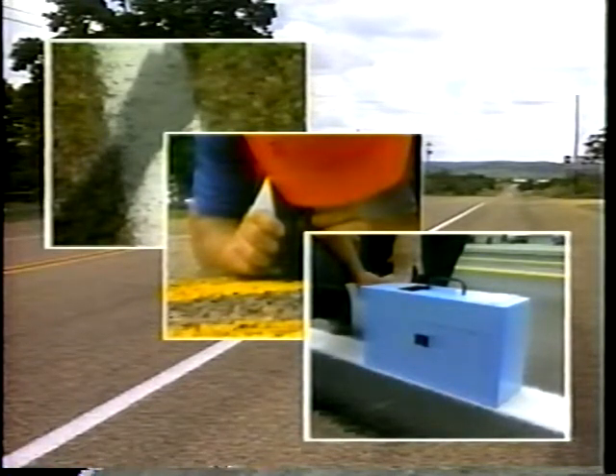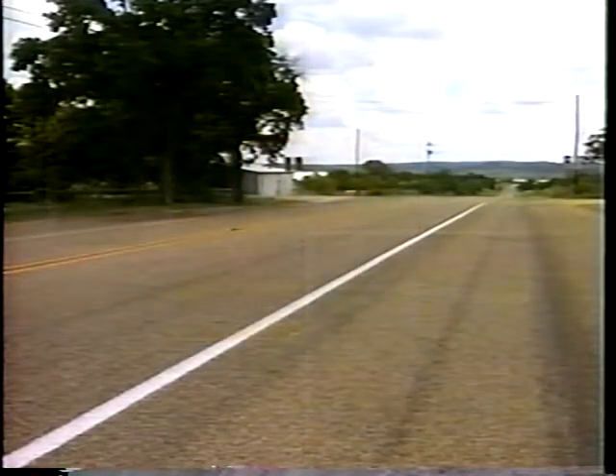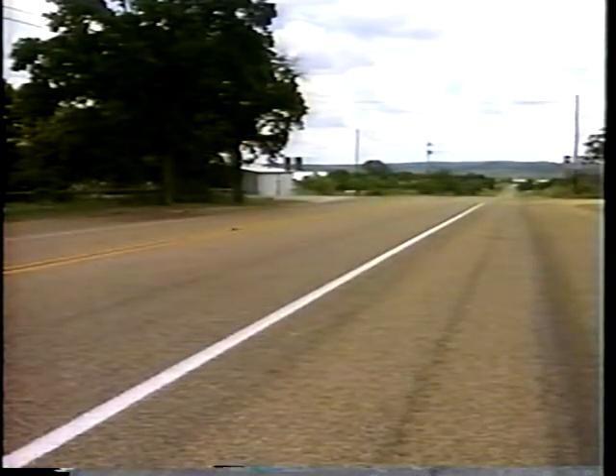The sunlight shadow technique may be used when the sun is from 20 to 80 degrees above the horizon. View the markings along a plane parallel to your shadow. As your shadow touches the marking, look for conditions that indicate excellent bead application and nighttime visibility. The stripe should give a smooth, uniform retroreflectance that makes the entire surface of the stripe appear to glow.